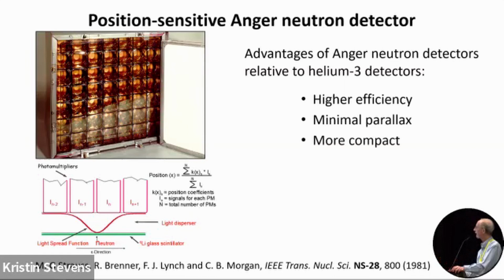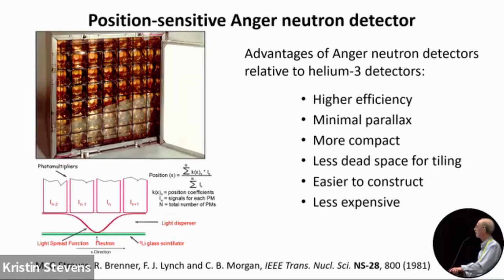It's more compact, with less dead space around the detector for tiling several detectors around the sample, easier to construct and less expensive. So it has a number of advantages, and particularly for getting to high Q, high resolution, small molecules, this detector still has very good efficiency, even at, let's say, half an angstrom neutrons.